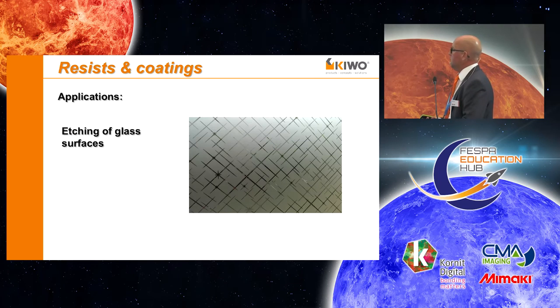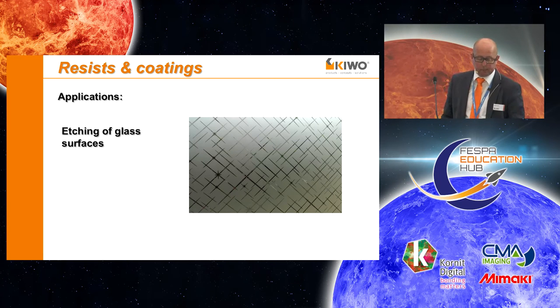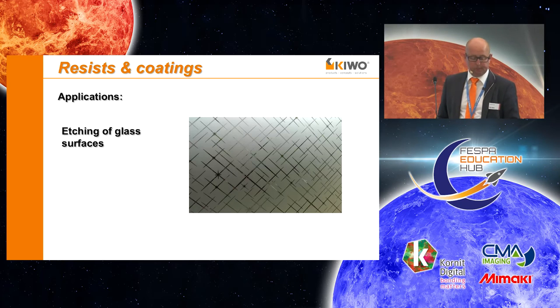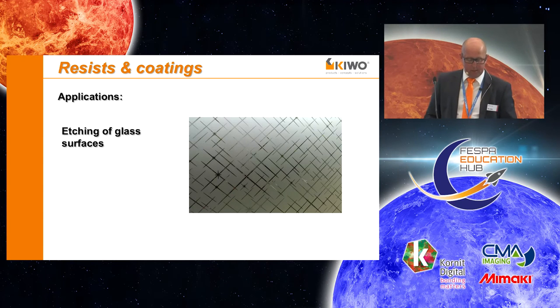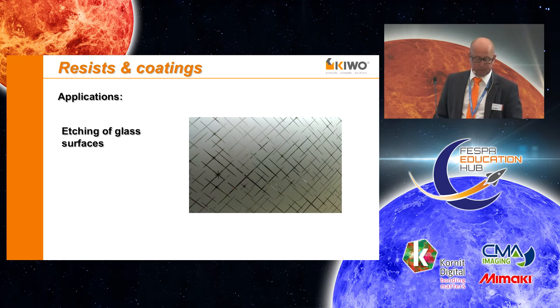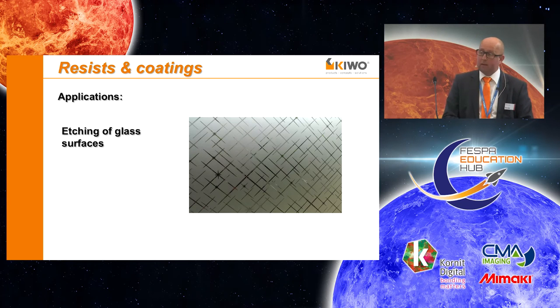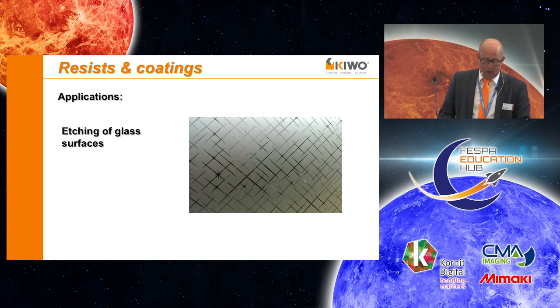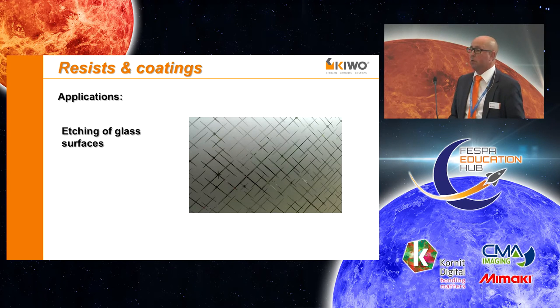The first application example is etching of glass — in my eyes, the finest art of glass matting. The glass surface can be matted with hydrofluoric acid. Depending on the length of exposure to the acid, the matting can be varied. The glass surface is matte and still transparent. To decorate glass by etching, a hydrofluoric acid-resistant mask is necessary. The resist can be applied by screen or pad printing and can be removed with special solvents. This application is suitable for flat and hollow glass.